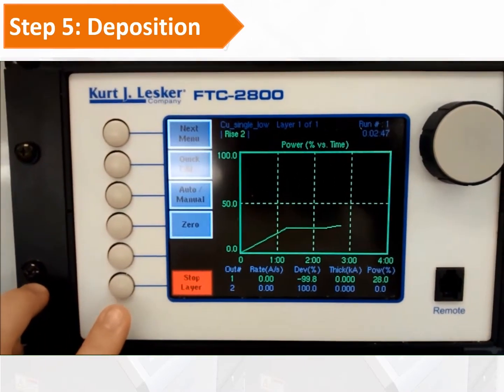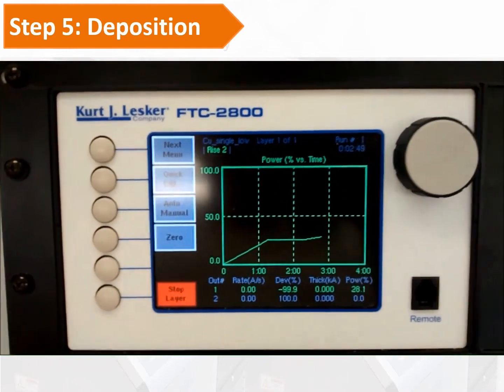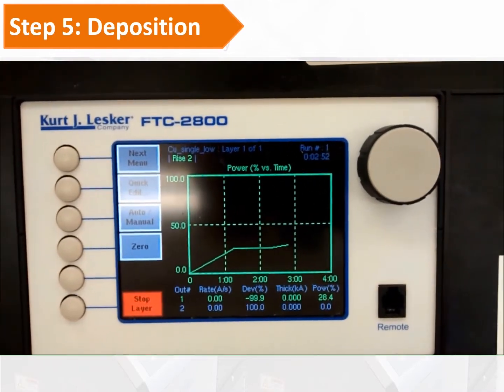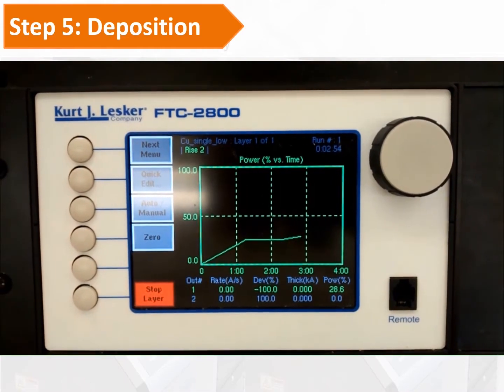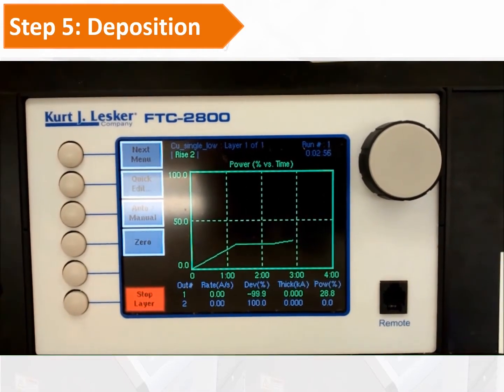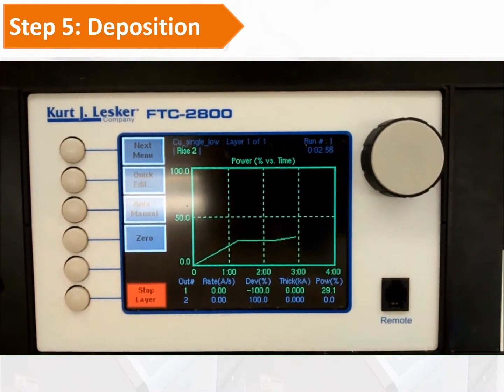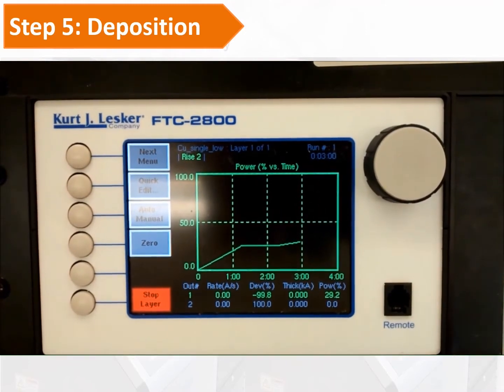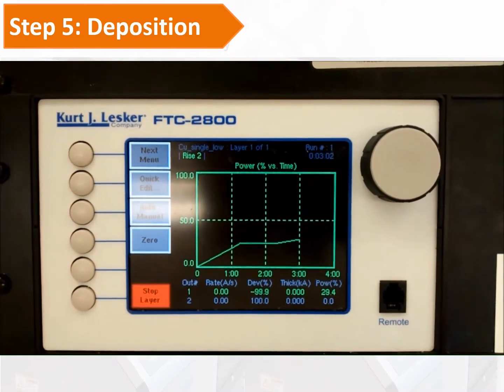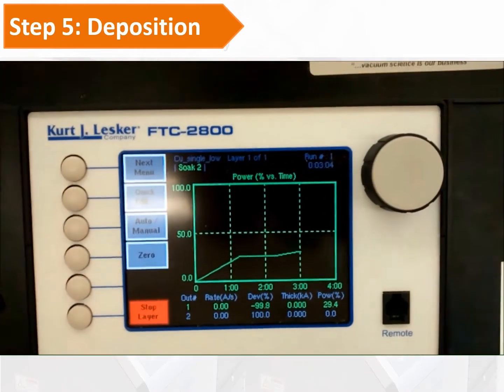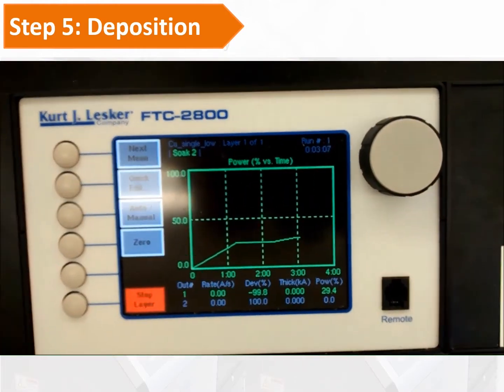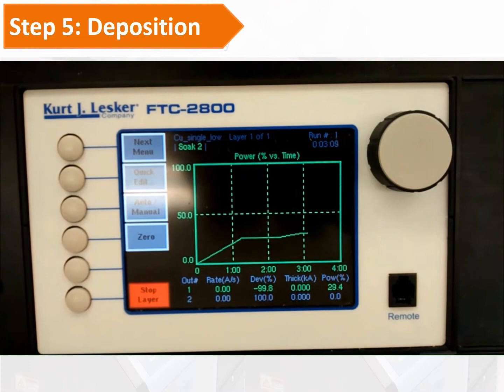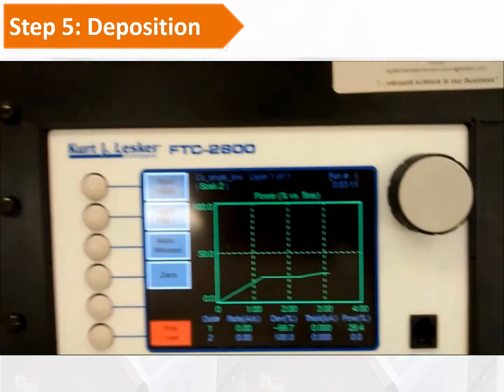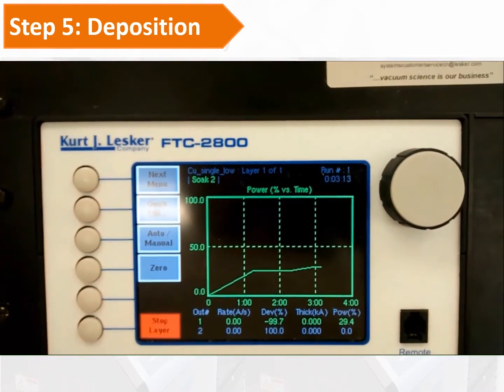And if you find any unusual situation during the deposition process, like the rate keeps decreasing but the power keeps increasing, or you find your boat is melting, you can just press the stop layer. It will stop your deposition process. And you can report to staff, and staff can help you figure out what the problem is and fix the issues.